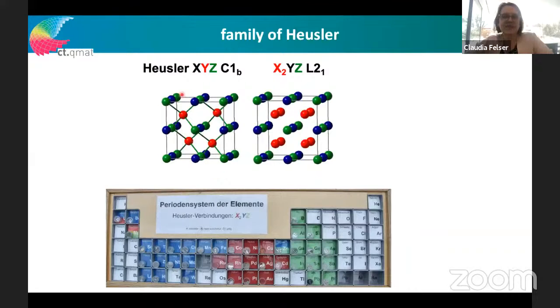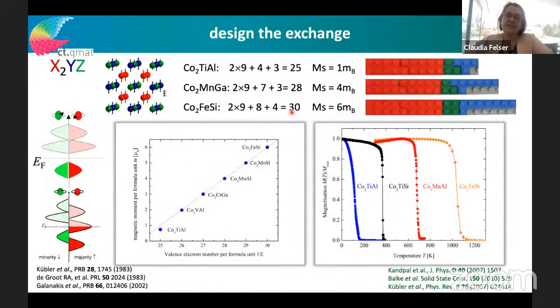You know that we have two groups of materials: the half Heusler compounds, which have the composition 111, and the full Heusler compounds, which have the composition 211. You can use many different elements to build up these crystals, and you find many good magnets, because at the end of the day, as I told you, we want to see this giant response, like a giant Nernst effect. We want to have it at room temperature or even higher, so it's good if these materials are magnetic at room temperature. And this is the case for Heuslers.